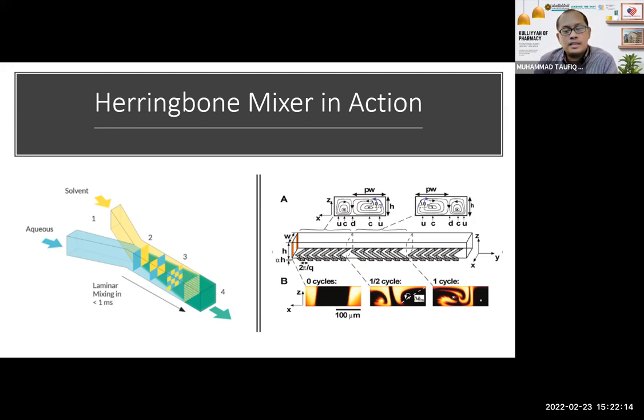Now, the herringbone mixer takes care of this by actually churning the flow. You can see that at half cycle there, the first 1/3 of the channel is starting to warp, like they try to twist it, but only 1/3 of the channel, and the rest, 2/3 of the channel, is only starting to warp. But coming to one cycle, it immediately switches. The initial 1/3 of the breadth of the channel suddenly changes to the 2/3 of the channel, and then becomes more properly mixed.